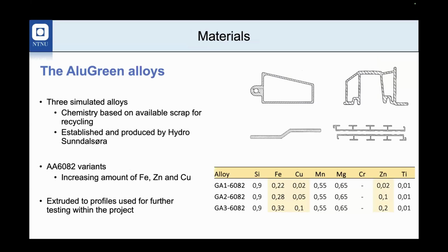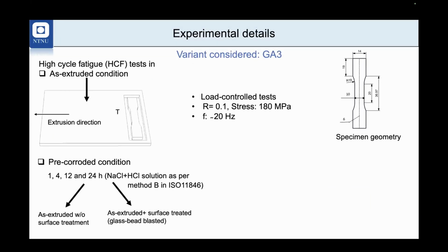To do that, first of all, let me introduce the type of alloys that we use. Basically, we use three simulated alloys, where, rather than using post-consumer scrap, we systematically increase the impurity elements like iron, copper, and zinc, so that it resembles post-consumer scrap. The material is available to us in the extruded condition. What we considered is the variant GA3. This variant has the highest amount of the impurity elements in terms of iron, copper, and zinc.